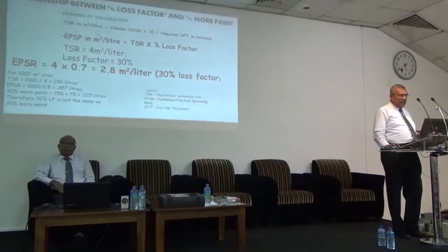If you look at this calculation, you see everything depends on volume solids. So if you take a low volume solid paint, you need more paint. If your loss factor is high, then you need more paint. So this is a common relationship.